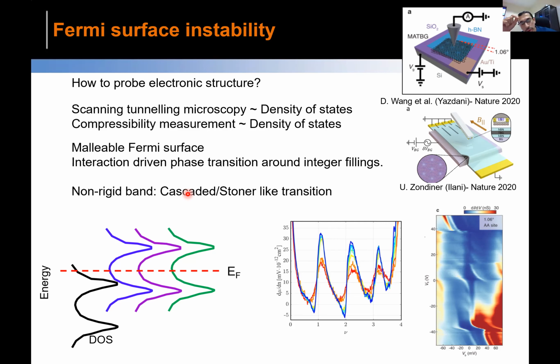And people have found, even at the Hartree level, if you do the calculation of the band structure, the stability of the band structure gives you this kind of transition around these integer fillings. So this is the doping level I was talking about. What is this integer filling here?